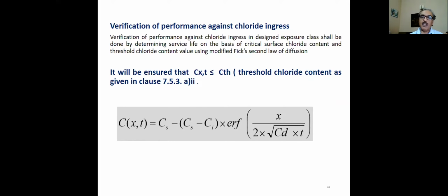This is because in case of carbonation, at many places the propagation time is very long, say 10, 12 years. But in case of chloride, because moisture is mostly available, the propagation time is less. So that has been ignored, and threshold value has been taken as the limit state.